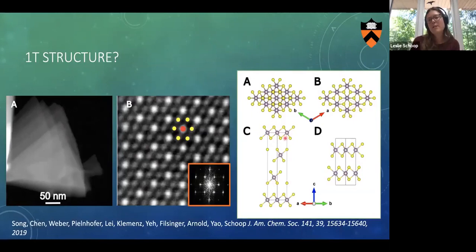So if you say, okay, we started with the structure and we took out the sodium, if you look at the top of this, we wouldn't expect different spots for sodium and sulfur because they're found on top of each other. So what must have happened is that the stacking changed and we see something like that, where sodium is arranged by the six sulfurs exactly as we see here. And that would have been awesome. So we look at it, we're like, great, this is the structure of 1T MoS2, and we made 1T MoS2-type chromium disulfide, how cool. But yeah, the story is not always that simple.